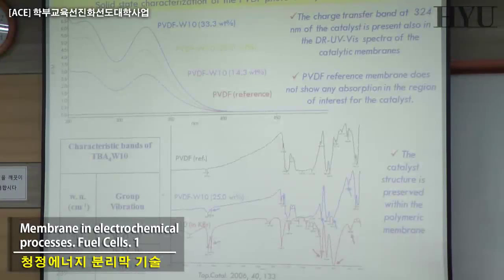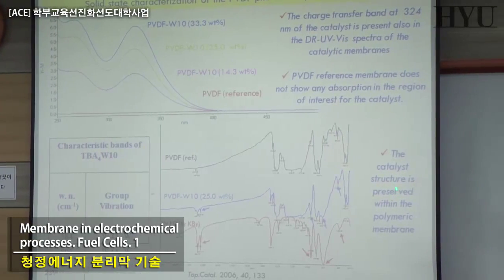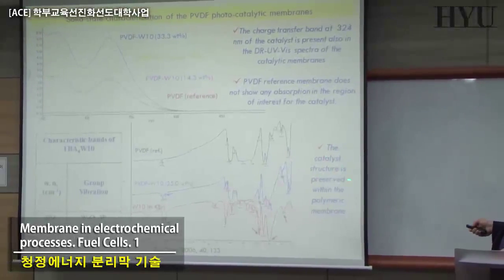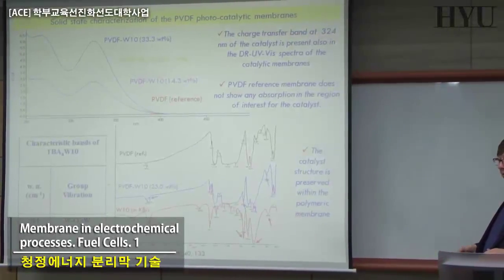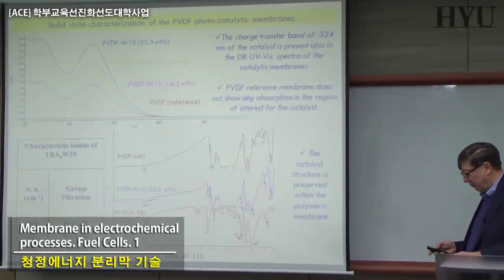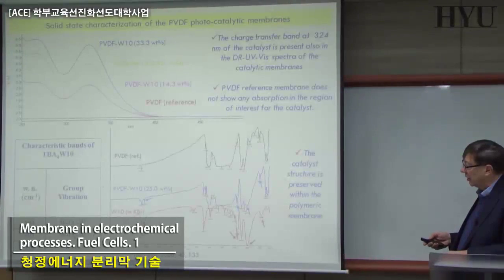After making the membranes, you have to check what I was mentioning before, and be sure that your catalyst is still acting as the catalyst that you were aware of before. So you have to check the different levels of absorption in the region of interest, in the frequency of your radiation. And you can see here, by the infrared, that the catalyst structure is well preserved in this PVDF membrane that we have been testing in this case. So that is one of the things that has to be done.